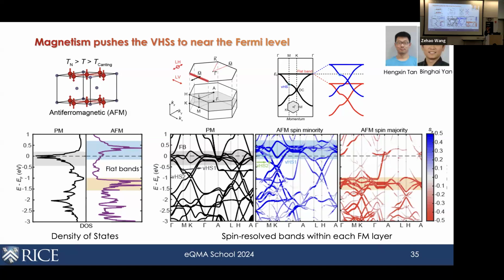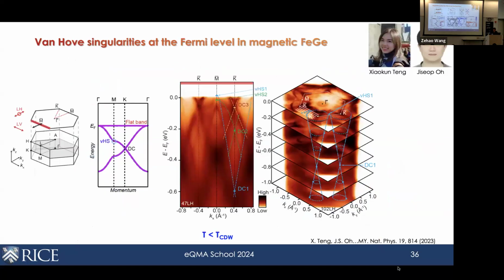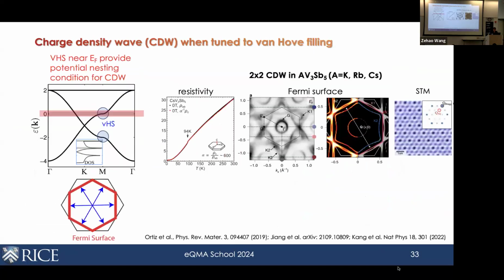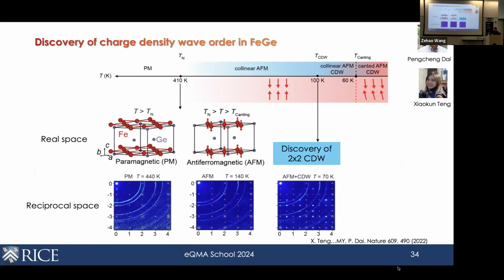That's with respect to the normal state. Here, I didn't label this, but this is the L direction and this is the H direction. This is the magnetic Bragg peak, and then this is the CDW which appears, which is 2 by 2 in the in-plane direction.